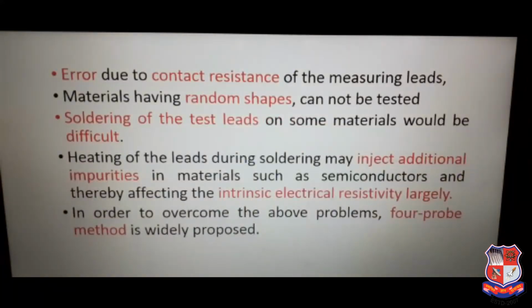Error due to contact resistance of the material leads is introduced in this 2-probe method. Materials having random shape cannot be tested. Soldering of test leads on some materials would be difficult. Heating of the leads during soldering may inject additional impurities in materials such as semiconductors and thereby affect the intrinsic electrical resistivity largely. In order to overcome the above problems, the 4-probe method is widely proposed.